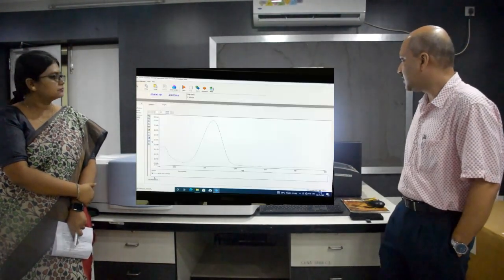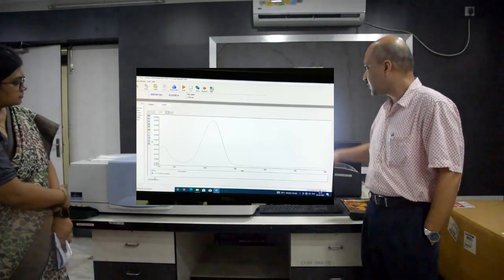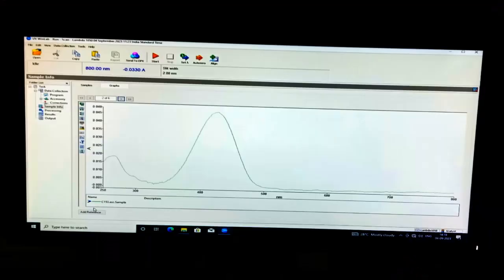For example, here what we can see is a typical spectrum of a molecule, coumarin 153, dissolved in methanol, and one can clearly see that this is a baseline, and then there is a drastic peak around 420 nanometer. So what that means is the sample is absorbing the radiation of 420 nanometer, and from there, if we know the molar extinction coefficient, one can determine the concentration of the solution.